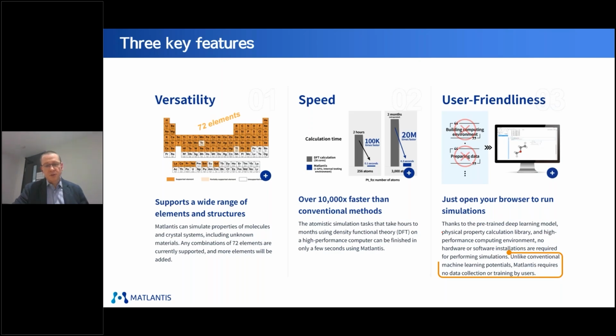The speed, of course, as I just mentioned on the previous slide, is about 10,000 times faster than what you would obtain with DFT. So you see here on the screen a very simple example using a platinum FCC cell, where you have 3,000 atoms. It's not something you want to do with DFT, but with Matlantis, that would take about a fraction of a second to complete a single point energy calculation.